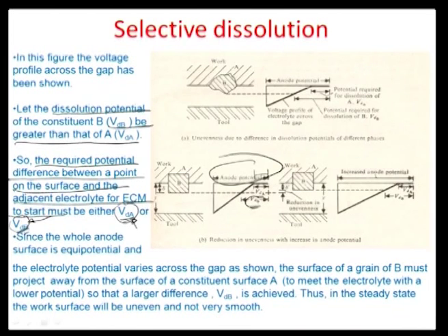Okay. So, VDB, the amount of available anode potential, would be available only at a certain distance away from the anode. Okay, it cannot be near the anode. So, this would result in an auto roughening, because VDB, the phase B, would get dissolved away only when the voltage that it meets with is VDB. Okay. And as you see from this particular potential trend here, the effective anode potential is a smaller value VDA available at the surface, and this is a linear drop, of course, because this is an ohmic drop. Okay. And so, the available potential nearer to the tool surface is more in comparison to that away from the tool surface, right. And so VDB will never get dissolved away in the anode surface